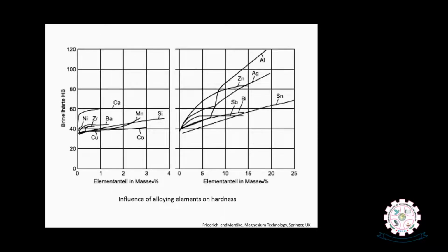This is another kind of study where we can see the effect of addition of alloying elements on altering mechanical behavior, mechanical properties. For example, hardness, if you measure, addition of these alloying elements in varying percentages has a significant effect on increasing the hardness. For example, if you take aluminum, it almost increases 2 to 3 times when we increase the percentage of aluminum in magnesium alloy.